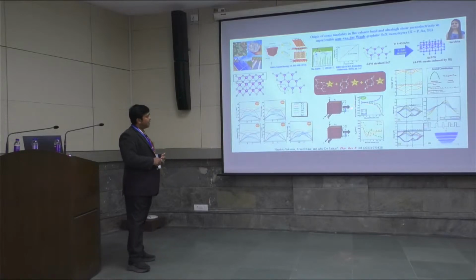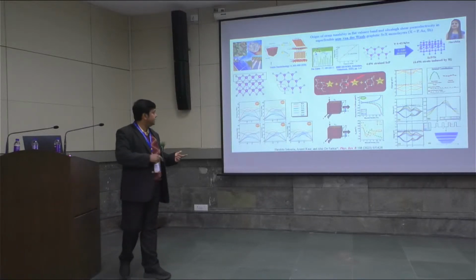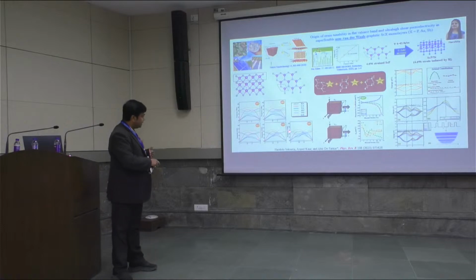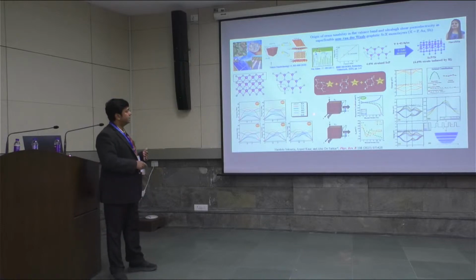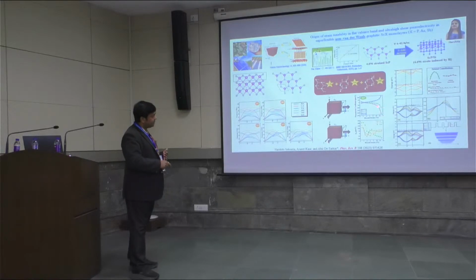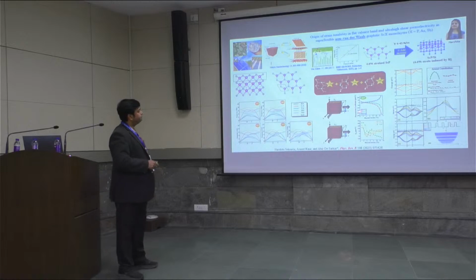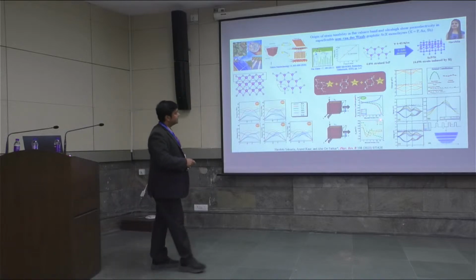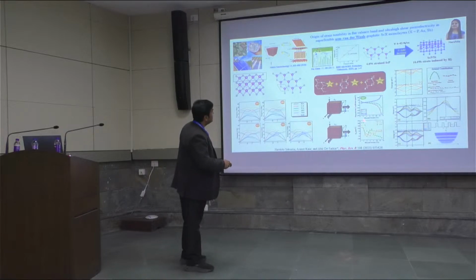Right? And so under the application of biaxial strain, we find that there is a complex mixing of these three phonon modes. They are most sensitive to the application of strain. The other phonon modes are relatively insensitive to the application of strain. And that is what is understood to enhance the shear piezoelectric coefficient in these monolayers. And so a systematic variation is observed in the piezoelectric coefficient D16 with the application of biaxial strain. And under biaxial strain, the piezoelectric coefficient D16 exceeds that of the beta glycine molecule, which shows the highest D16.